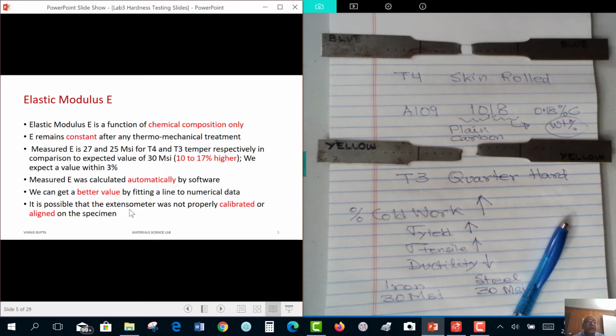It is also possible that the extensometer was not properly calibrated. I don't believe so because I set the calibration to none a long time ago, so I don't think anybody has messed up with the calibration. Possible they have. Another possibility is that the extensometer was not well aligned on the specimen. I did not conduct this test. This was done by Mr. Humphrey.